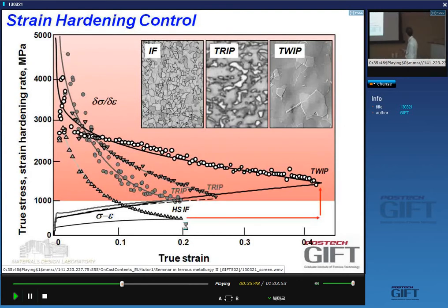In this case, first of all, in the case of TWIP steels, we have resolutely gone from ferritic alloys to austenitic alloys. And we're in a system with a much lower stacking fault energy. What is interesting is that the TRIP steels, which may not give such a huge improvement, are also pretty interesting, because they achieve these strength levels and these ductility increases at relatively low alloying contents. This is a route that is gaining popularity, and this is one of the reasons why we are seeing this vast and very diffuse cloud of compositions, where people are trying to see which one is the solution.